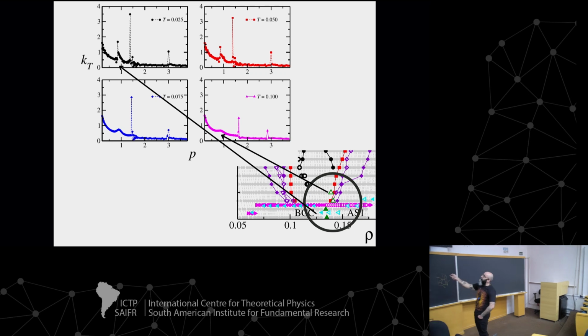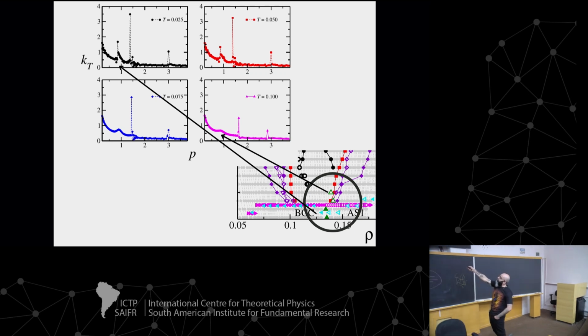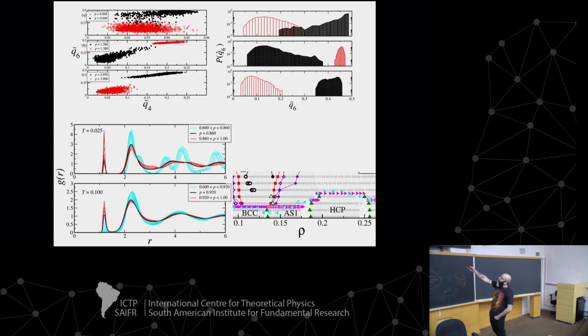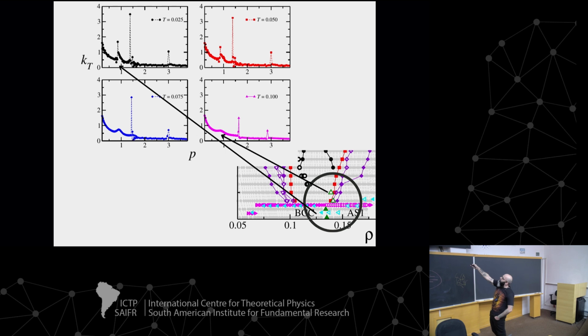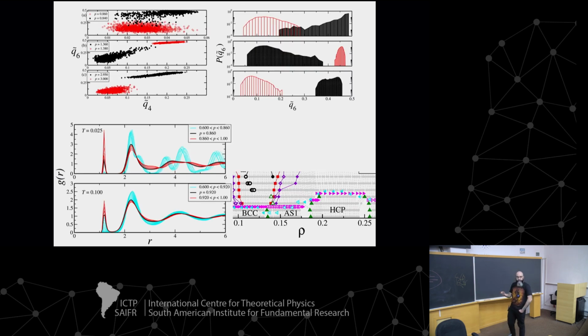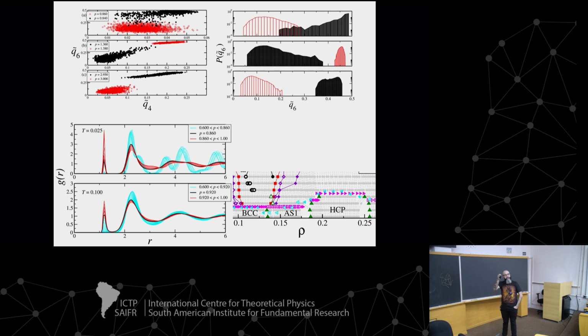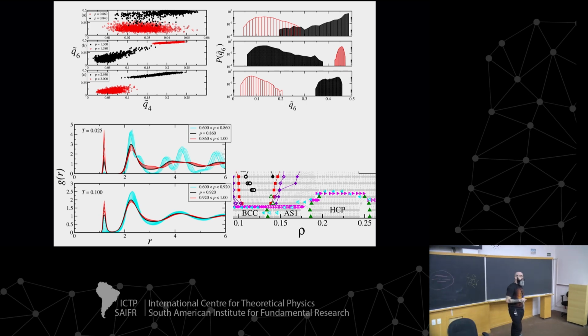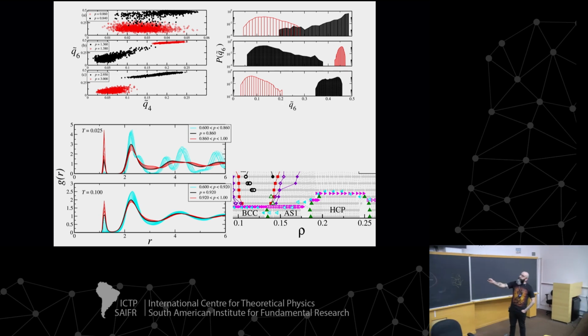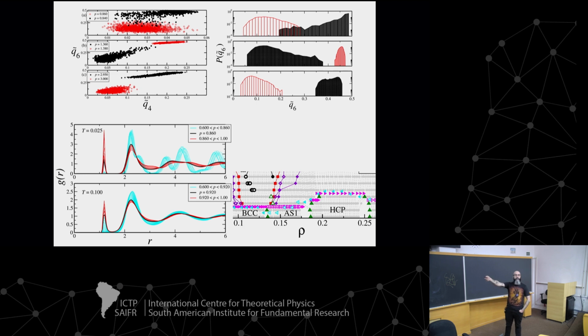And obviously, we tried to understand. Here we have a jump, and here we have this kind of bump. What's different between these two cases, between the bump and the discontinuous regime? So we go back to the orientation of the system. So here, and also the translational order that you can analyze by the g(r).